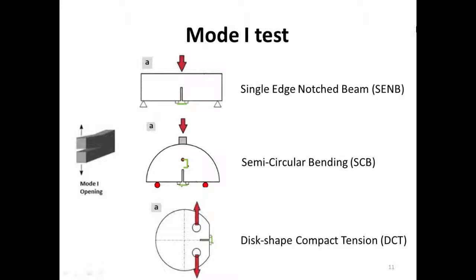So for the mode 1 test, there are a few primary tests. The first one is called the single edge notch beam. So you have this beam in a 3-point bending test. What we do is we put a notch here so the crack will grow along this notch direction.